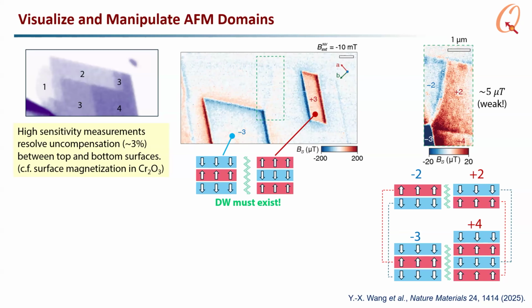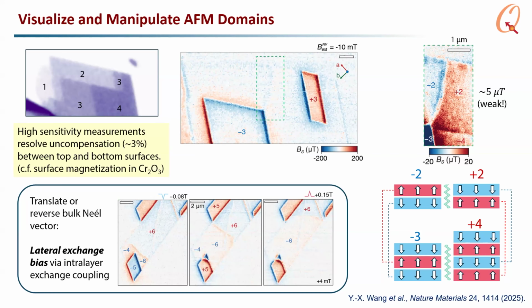So actually, we can see a very weak stray field on the bilayer with high sensitivity measurements down to 5 microtesla. So it's about a 5 microtesla stray field. This is a 10 times higher sensitivity measurement than when we image a large region. So this allows us to see antiferromagnetic domain walls. And what that's coming from is that when you make these 2D samples, the top and bottom surfaces are never perfectly compensated. So it is somewhat similar to the surface magnetization you see in bulk chromium oxide, but for these 2D van der Waals materials, it allows you to see where the domain walls are, and it allows you to use that slight bit of uncompensation to actually drive the domain walls as a function of a magnetic field.